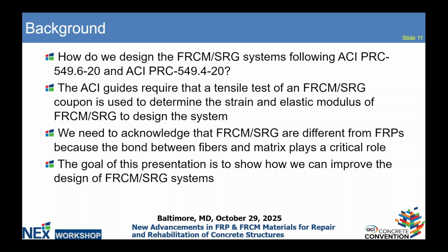So what are we doing in ACI 549.4R and 549.6R, which are the two documents that are the guide to design FRCMs for concrete and masonry? The ACI requires that we use a tensile test of a coupon made of FRCM or SRG. And I actually didn't mention SRG. It was defined there. It's the same, but the fibers are steel. And the idea is to pull this coupon to get some properties that then are used to design. And in particular, from this test, ACI basically determined the strain and the elastic modulus to use in the design, typically in the cross-sectional design.